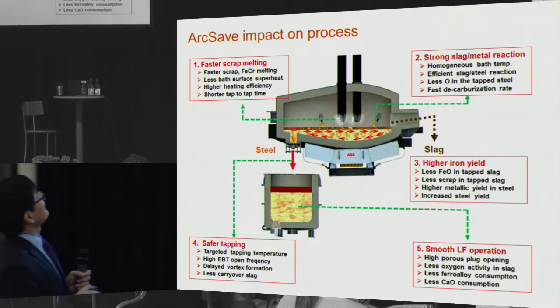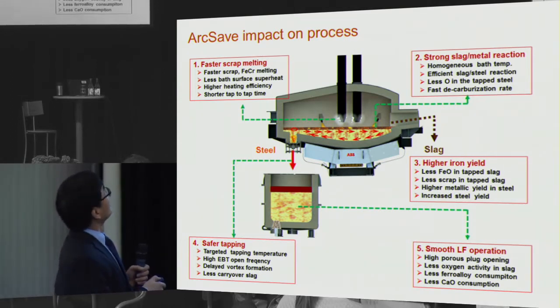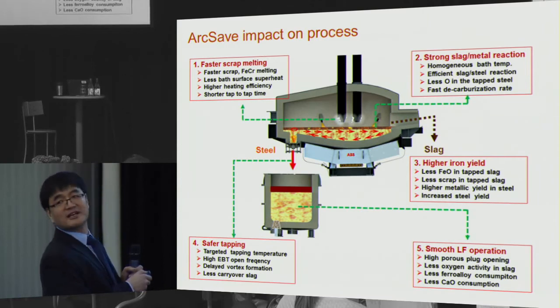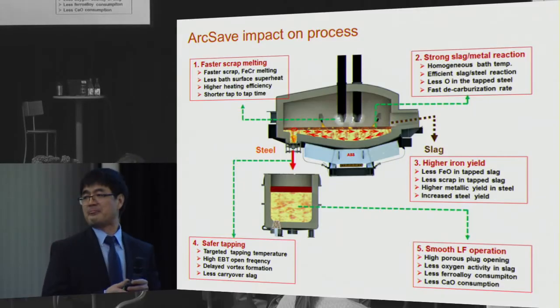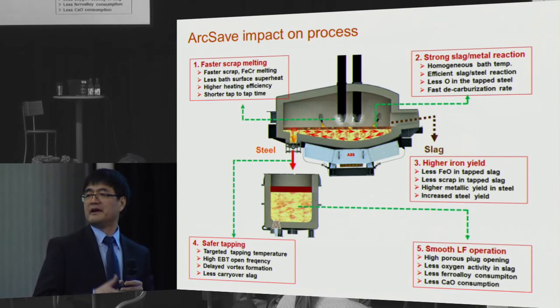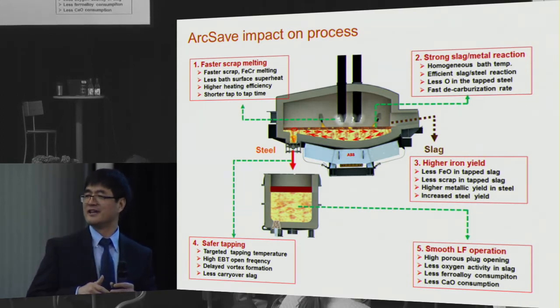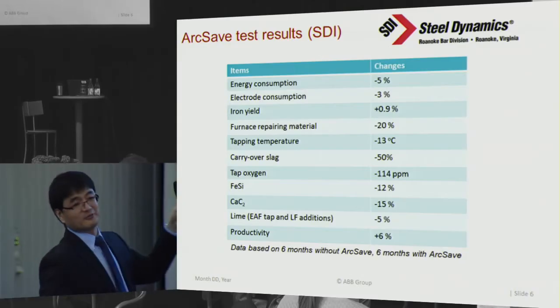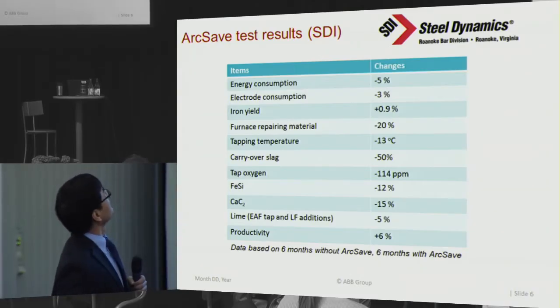Another effect with the EBT furnace is that with this direction of movement, the vortex, you see this circle here, is reduced. About half of the carryover slag is reduced. This reduces the oxygen and saves ferroalloy in the later furnace position. This is a typical phase. Of course, if you are interested, we can discuss it in detail.